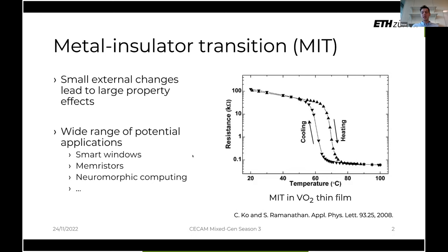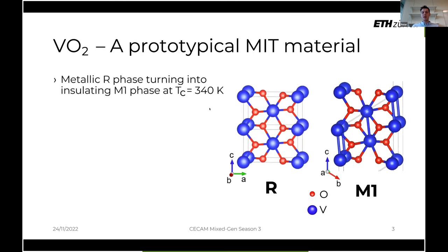And indeed, vanadium dioxide is a prototypical material that undergoes a metal-insulator transition. It goes from a metallic rutile phase, denoted with R, and at the critical temperature of around 340 Kelvin, which is very close to room temperature, it changes into a monoclinic insulating phase labeled M1.